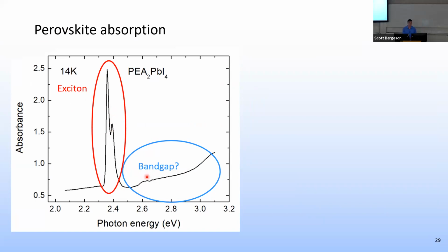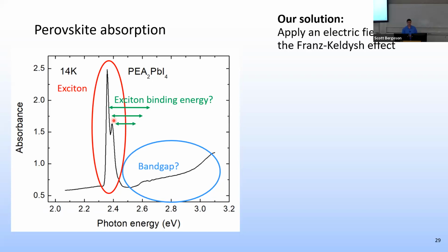And there's been a lot of disagreement in published reports in the literature for lots of different types of perovskites about what the band gap is. And the binding energy is the difference between the excitonic absorption and the band gap. That's a really important quantity to know. For example, in a solar cell, you're producing an electron hole pair. The electrons are going one way, the holes are going the other way. So you have to separate the electron and hole, which means you have to overcome the binding energy. And so you better know what that binding energy is when you're designing your solar cell. But it's really hard to tell. So a lot of what we've been doing is to try to solve this problem.